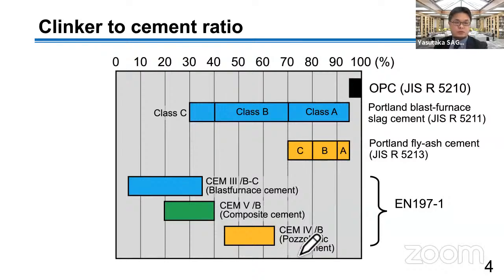So this figure shows the clinker to cement ratio percentage of cement types in Japan and the European standard. Clinker to cement ratio is defined as the mass ratio of cement clinker to cementitious material. In other words, 100% means almost pure Portland cement, and 0% means without cement clinker.